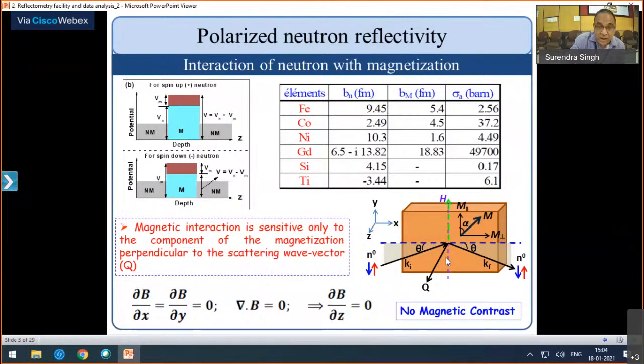This is one thing, and this is valid for diffraction also - if the neutron spin or the magnetization of the sample is along the q direction. Q is defined in this way, like ki minus kf. It is out of the plane for thin films. Then we cannot see anything about the magnetization in the film, because of this law which says divergence of B equal to 0 means we don't see any contrast or variation if we apply magnetic field along q.